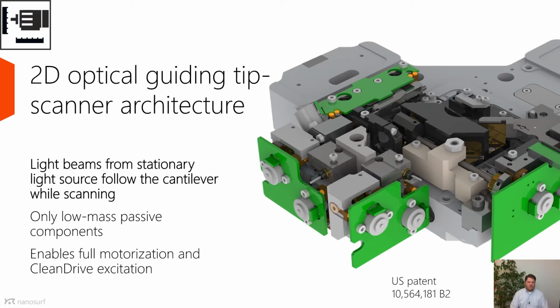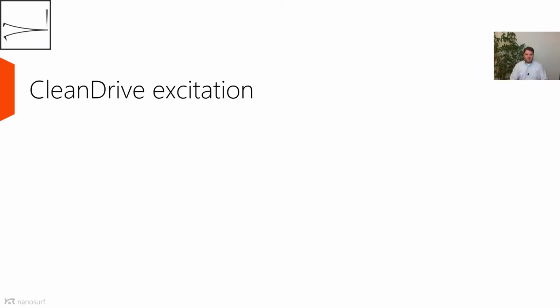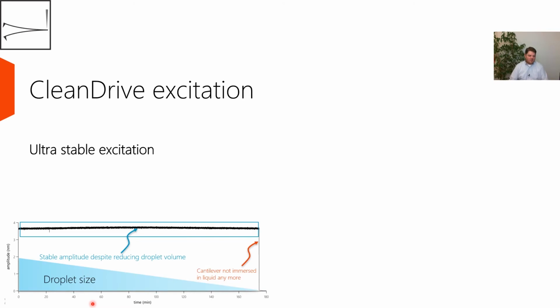So what is actually clean drive excitation? Clean drive excitation is a very stable way of exciting the cantilever. So what you see here is we're driving the cantilever at an amplitude of 3.5 nanometers, and the cantilever is immersed in a little drop of liquid. And as we let the drop of liquid evaporate, the amplitude doesn't change a lot. It only changes here once the droplet is basically evaporated and the cantilever is not immersed in liquid anymore. And this is over the course of almost 3 hours. In liquid, with the typical piezo excitation that we used before, this curve would change a lot.